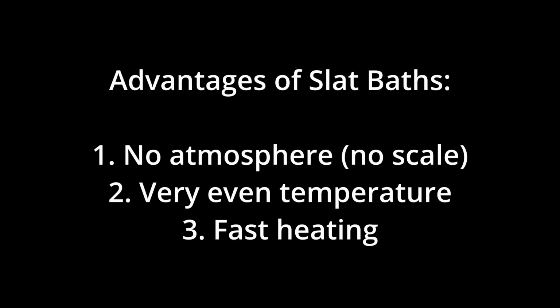Another big thing is the rapid heat transfer. So liquid is much better at transferring heat than air. This is why it's extremely scary sticking your hand into boiling water at 212 degrees Fahrenheit, 100 Celsius. That is way scarier than sticking your hand into an oven, that's in air, even at much higher temperatures. You stick your hand into a 500-degree oven all the time for short periods of time so that you can put things in and take things out when you're cooking them, and that's not scary at all because air does not transfer heat as rapidly. So with salt pots, you can heat up the steel very fast.